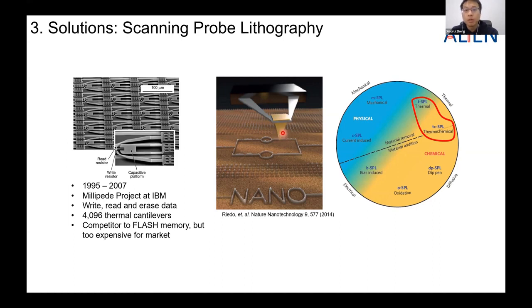So by the strong interactions between the tip and the polymer, we are able to create nanostructures on the polymer, and then we can further transfer the nanostructures into the substrate of choice. Because we are using a thermal mechanism to introduce this nanostructure, we call it thermal or thermochemical scanning probe lithography. And of course, depending on the mechanism we are using, there are many different types of scanning probe lithography techniques, like physical or chemical mechanisms here.